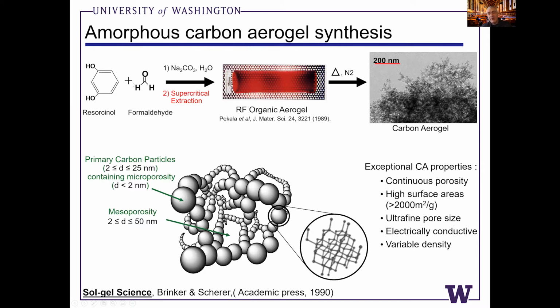This is a gel that forms due to sol-gel cross-linking. There are a number of electrophilic addition steps and condensation, polycondensation reactions where we produce some water in this reaction, but effectively we make some hydrocarbon gel that has a lot of hydrogen and a lot of oxygen from the precursor molecules. So to get rid of the hydrogen and oxygen, we pyrolyze the hydrocarbon aerogel at very high temperatures, typically above 1,000 Celsius. In an inert atmosphere, it could be argon or nitrogen, and we make an amorphous carbon aerogel.